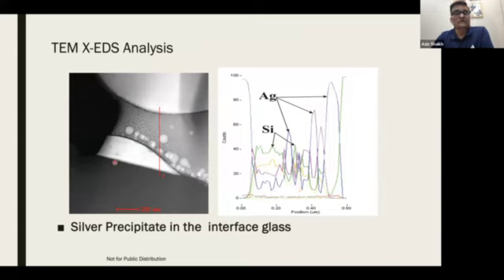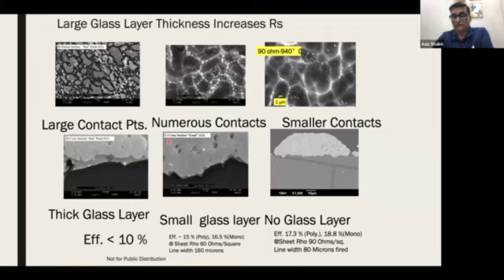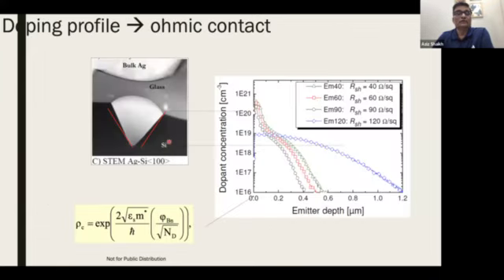So the interesting thing is, you have these grid lines. This is the silver particle, which is part of the grid line. And this is a silicon wafer where the charges are residing. So how do you go from here to here is the question. What you see here are the precipitates of silver on the surface of the silicon wafer. And then there is a glassy film in which there are also small precipitates. So they act as a conductive channel to transfer the electron from silicon to the bus bar or the fingers, as we say. Okay. And I'm going to skip this.